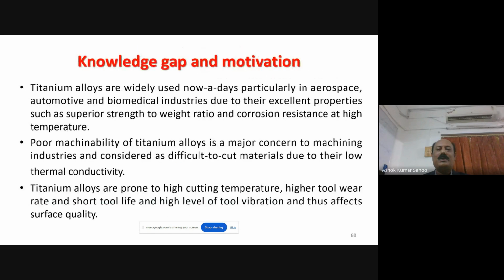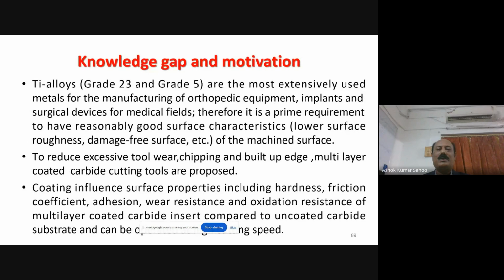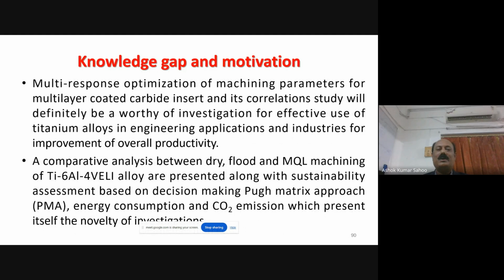And we know the titanium alloys are widely used, particularly in the aerospace, automotive, and biomedical industries due to excellent properties such as superior strength-to-weight ratio and corrosion resistance. Poor machinability of titanium alloy is a major concern. It is prone to high cutting temperature, high tool wear, and also built-up edge, and a high level of tool vibration also that affects the surface quality. To reduce the cutting tool wear, chipping, and built-up edge, multi-layer coated carbide inserts are generally proposed. So coated carbide inserts play a very vital role in this.